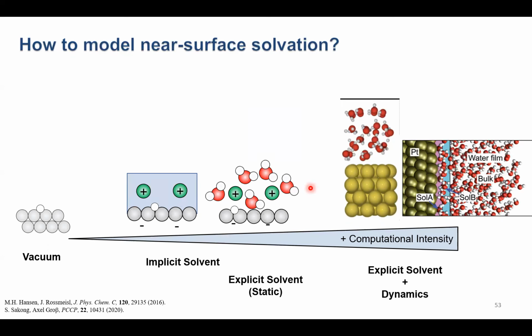One other comment that I'd like to make very briefly is I think we need to think very critically about how we model near surface solvation. There's many different ways to model the effect of solvent near a surface. We could totally ignore it and just model things in vacuum, or we could add hundreds of water molecules and look at their dynamics with ab initio molecular dynamics. And there's lots of methods in between. And I think roughly they follow this order of computational intensity, right? Certainly modeling things in vacuum is the easiest, and doing molecular dynamics of hundreds of water molecules near a surface is hardest.